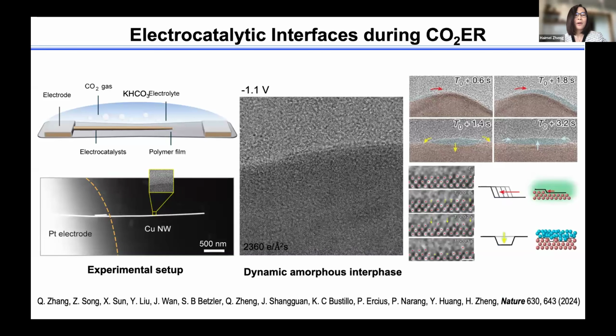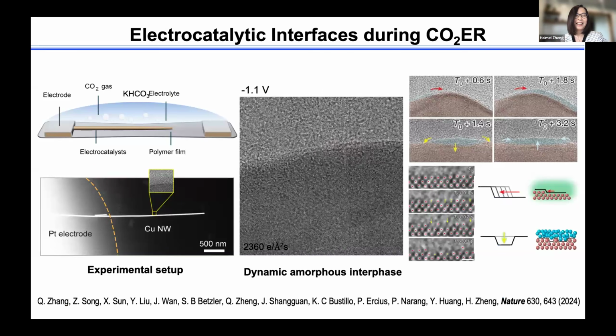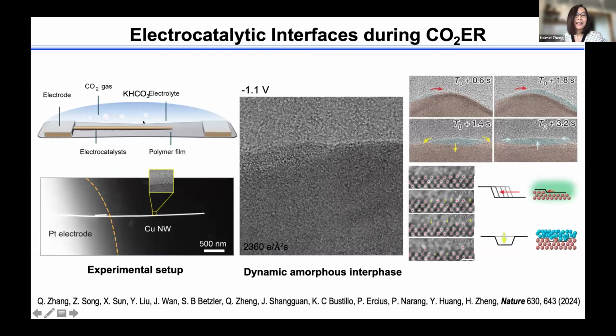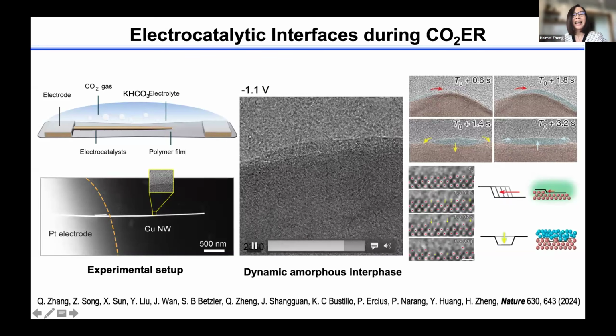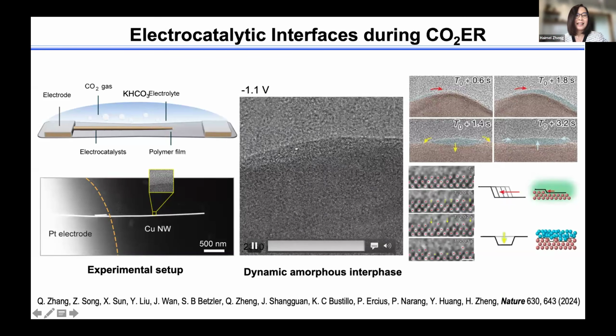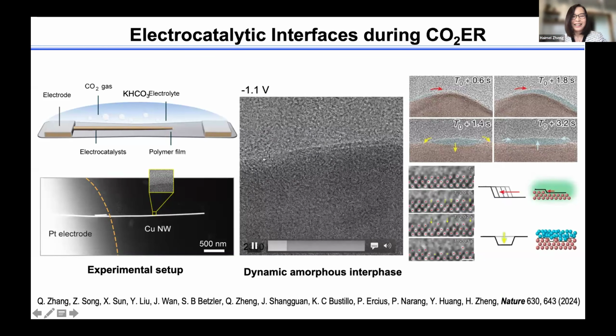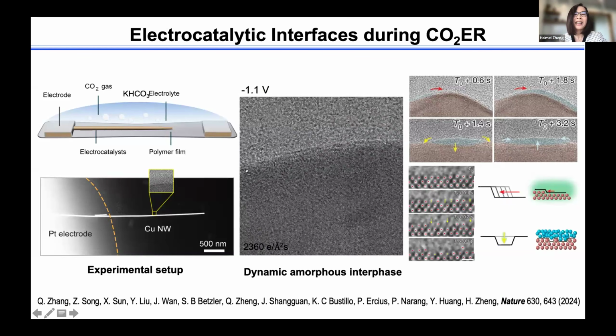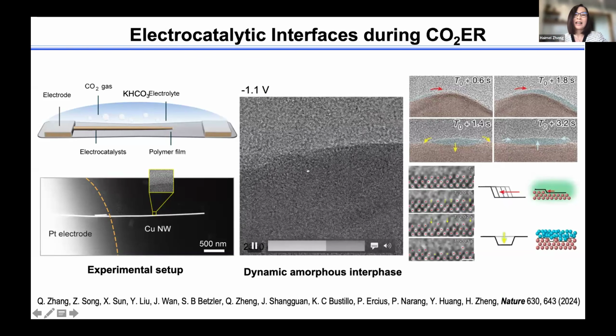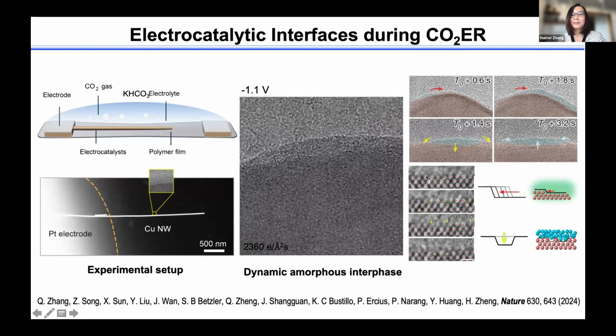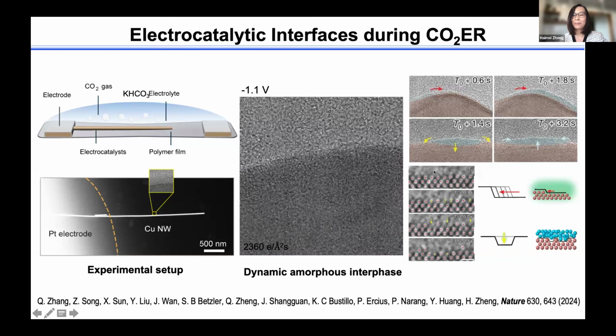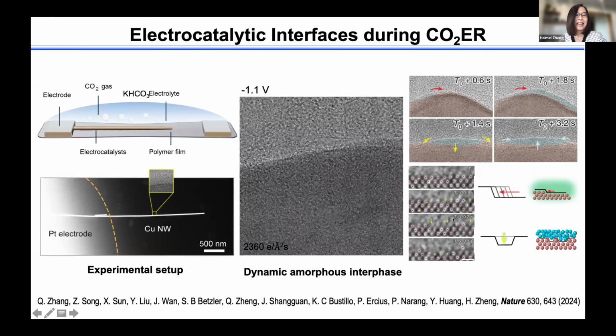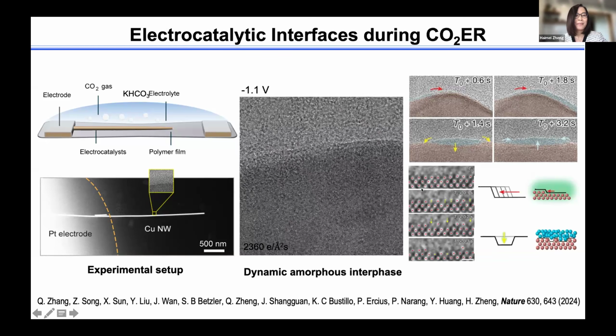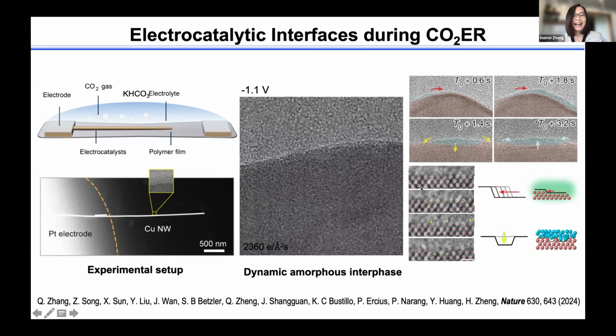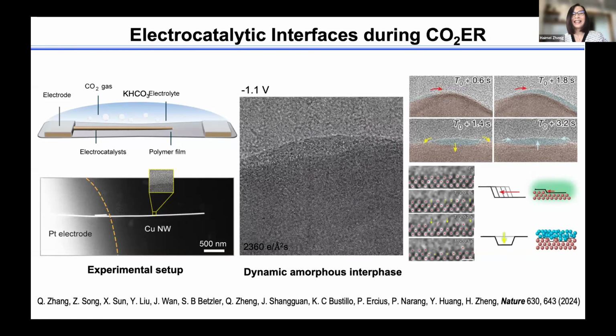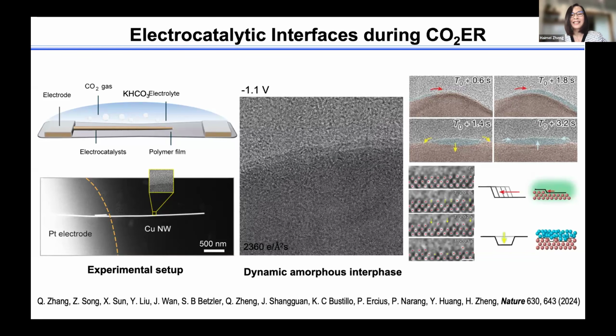And this is one example, shown very quickly. We found this copper nanowire catalyst during CO2 reduction showing very interesting dynamics. We found this amorphous-like, liquid-like state flowing at interfaces. It can move left and right, and it can also interconvert between the solid state and the amorphous state. Because we have high resolution, we can find the detailed mode of how it flows and how it interconverts. And this really represents the highest resolution dynamics in a very delicate, complex electrocatalysis system.